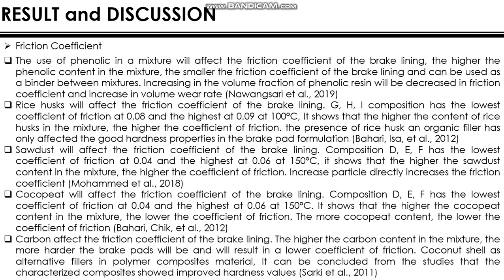Friction coefficient. The use of phenolic in a mixture will affect the friction coefficient of brake lining. The higher the phenolic content in the mixture, the smaller the friction coefficient of the brake lining, and it can be used as a binder between the mixture. Rice husk will affect the friction coefficient of the brake lining. GHI composition has the lowest coefficient of friction at 0.08 and the highest at 0.09 at 100 degrees Celsius. It showed that the higher the content of rice husk in the mixture, the higher the coefficient of friction.